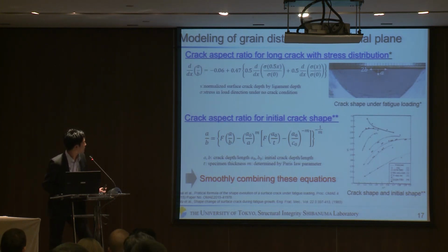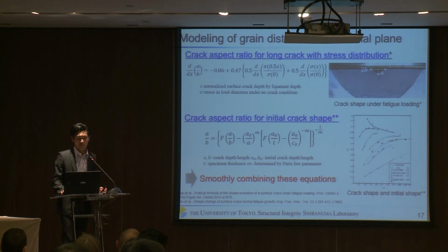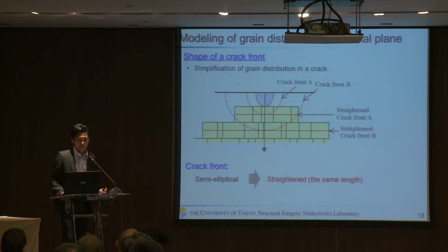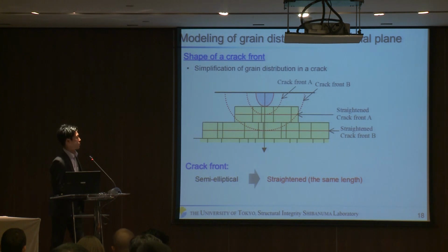This is for a long crack, but for a short crack, the initial crack shape is more important, so this equation is employed as well. In this model, these two equations are smoothly combined, and this change of aspect ratio is considered. Since, as I mentioned, the fatigue crack shape is semi-elliptical, and since it is complicated to model grain distribution considering the change of the crack ratio, we focus on crack fronts.